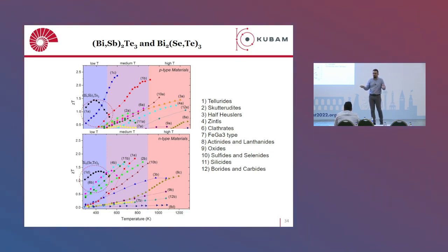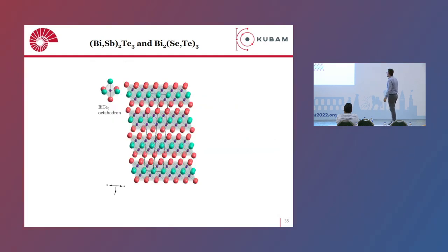These are the low temperature materials that are mainly used for Peltier coolers. So you can see that this is the P-type, this is for the N-type materials. For the low temperature, they are kind of the best materials. So the bismuth antimony telluride, BST phase, is very good for the P-type, and bismuth selenide telluride is very good for the N-type. So the others cannot compete, except for the magnesium antimonide so far.